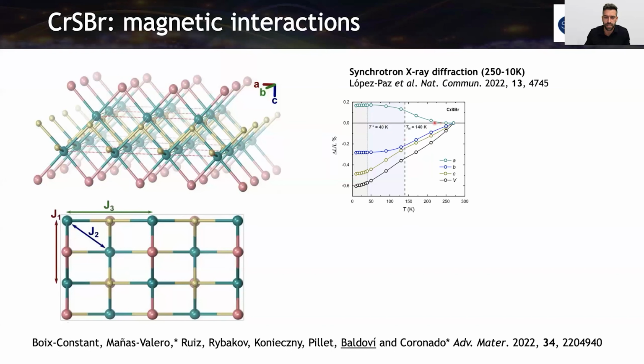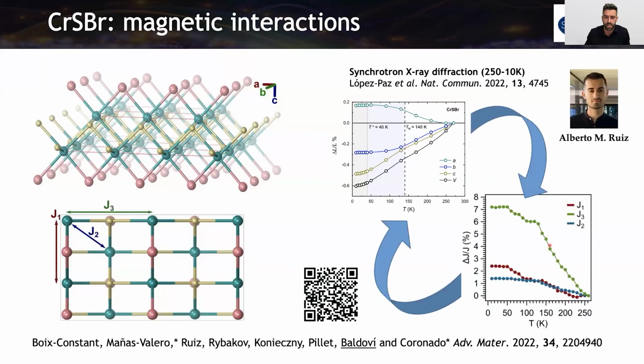And we can observe here that the A-axis is expanding when we go to low temperature, whereas the B and C axes are being compressed. We calculated, taking into account these lattice parameters, following the lattice parameter trend and relaxing only the atomic coordinates, and we were computing all these exchange interactions. We can observe that for all this range, J1, J2, and especially J3 are increasing. So the magnetism is driving this structure until it saturates at around below 40 Kelvin. The structure is not moving anymore.